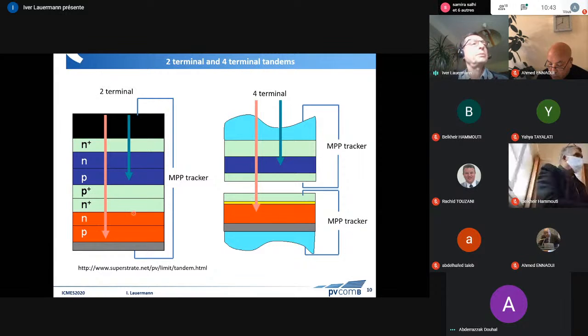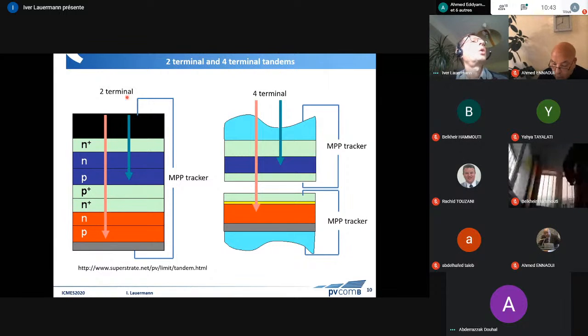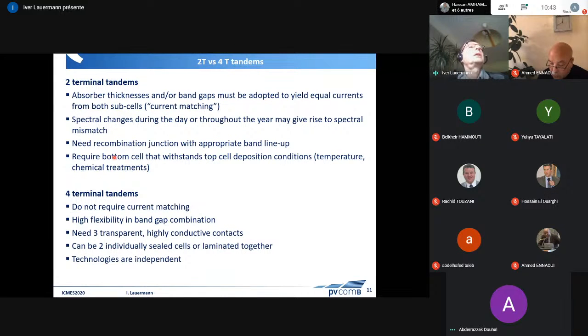We want to combine a bottom cell, a thin film bottom cell of CIGS, copper indium gallium diselenide, with a large band gap perovskite. Now, the advantage of having a 2-terminal is we don't need all these cables. We can make the cells in one go, so to say, in any kind of fabrication site where they have the glass substrates basically entering the machine on one side, and all the thin layers are deposited. At the end, we have the ready device.